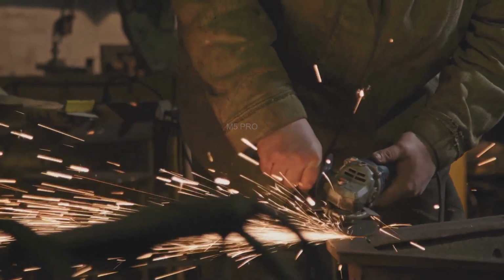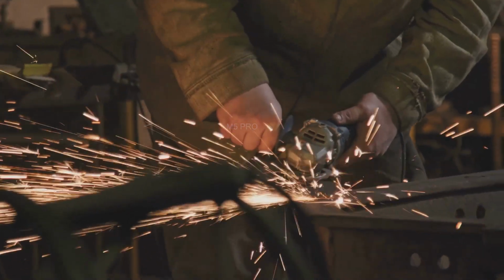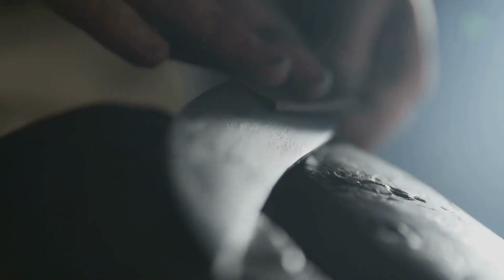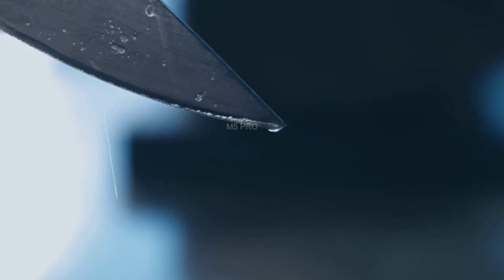Keep the blade moving constantly to avoid flat spots or uneven surfaces. Just like before, the blade is frequently dipped in water. Even with these finer belts, heat can build up quickly. We cannot risk overheating the steel and ruining the temper. As the blade moves through finer grits, its appearance changes dramatically. The dull satin gray starts to give way to a brighter, smoother surface. Depending on the desired final look, this can have many steps.